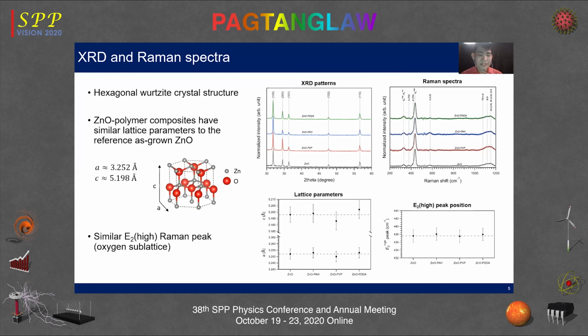The diffraction peaks of all samples, the ZnO and the ZnO polymer composites, are indexed with the hexagonal wurtzite crystal structure of ZnO. And also, we calculated the ZnO polymer composites that have similar lattice parameters to the reference as-grown ZnO. The calculated lattice parameter a is approximately equal to 3.252 angstrom, and lattice parameter c is approximately equal to 5.198 angstrom. And all samples are polycrystalline without any detectable impurity.